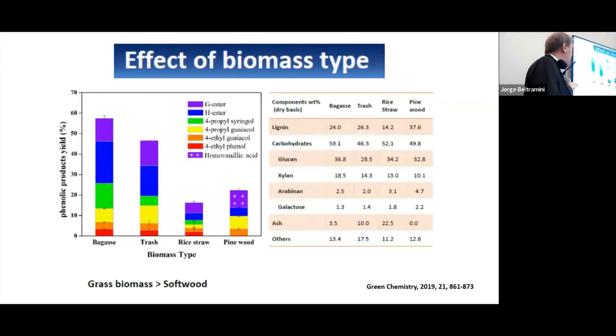Effect of biomass type: here we can use any type of biomass, but it's very important that bagasse and the trash are the two better than rice straw, because of the concentration of the G and H ester in the original lignin. So the composition of the natural lignin is very important if we would like to apply it in a process like this.